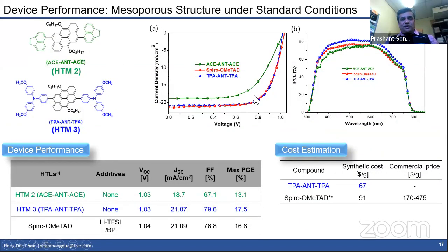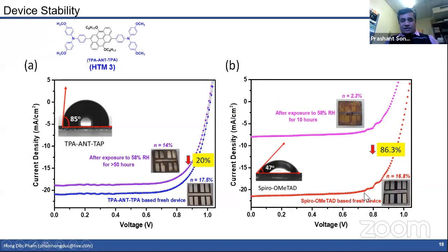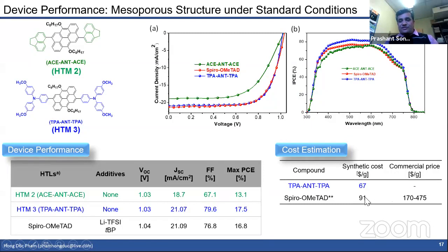Taking these other two compounds, we made perovskite solar cell devices in collaboration with Sagar Jain at Swansea University. The highest efficiency we could achieve was for one compound called HTM3, which is TPA-ANT-TPA, at almost 17.5%. The cost of this TPA-ANT-TPA is $67 per gram compared to the Spiro, which is $91. This is the commercial price which we determined by taking all of the starting materials into account. So these are two dopant-free materials, and we can get really high efficiency. For the Spiro, just for comparison, we have to add the dopants lithium TFSI and TBP, and efficiency-wise it is still lower than our devices.